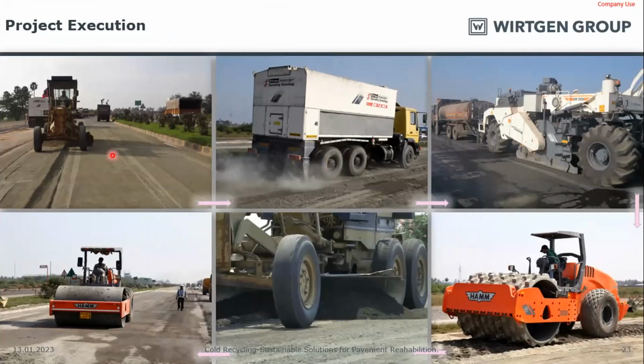Initially, on top of the damaged layer, we spread the crusher dust and then grade it to the profile. The second step is the cement spreader. It's a microprocessor controlled system where, depending upon the depth as well as density, it spreads the cement. So it is an automatic controlled machine. And next is the Wirtgen recycler. It granulates the existing asphalt layer along with the addition of bitumen and water. The bitumen and water tanker are coupled in front of the machine, and the machine pushes them. The bitumen will be preheated and stored in the truck at a temperature of 160 to 180 degrees Celsius as per the design.